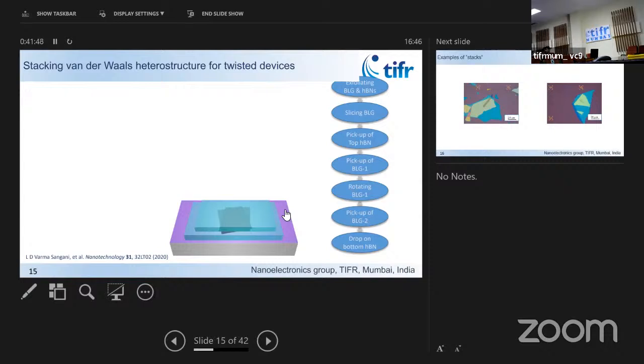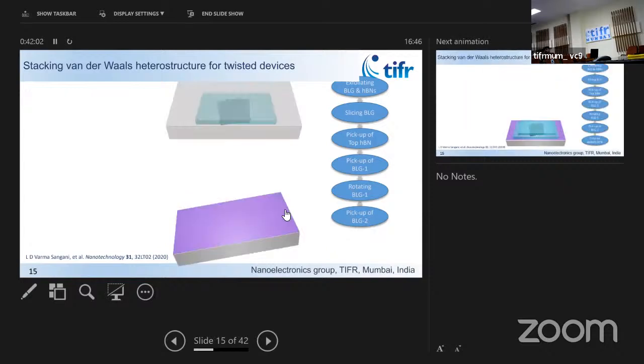Does the gap between the 2 determine the twist angle? No, the physical gap doesn't determine the twist angle. The twist angle you have to dial in at this stage. I rotate the motor, some geared stage, by 1.01 degree, 1.18 degree, and I get that twist angle.